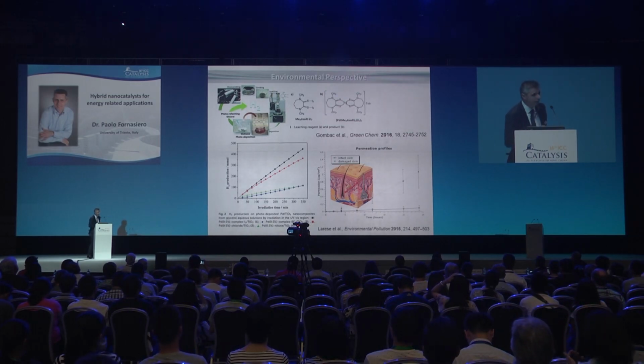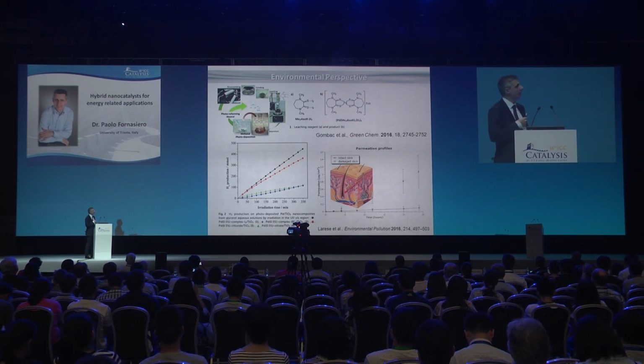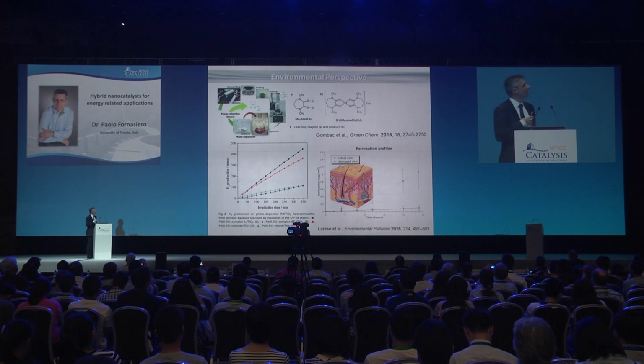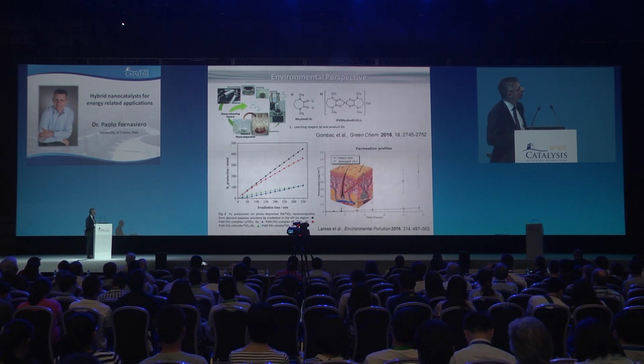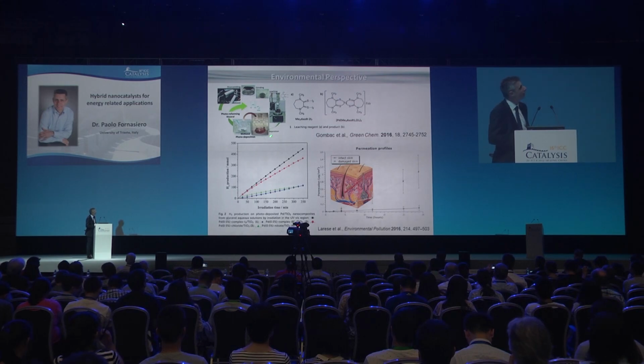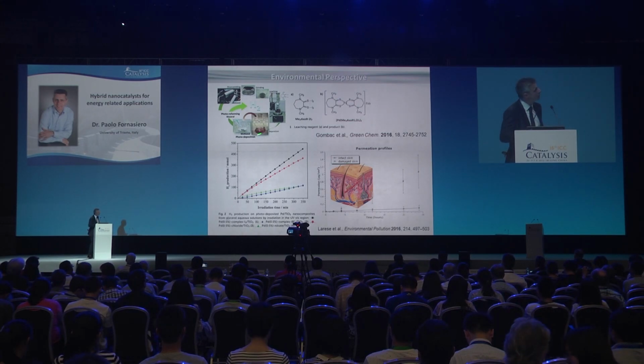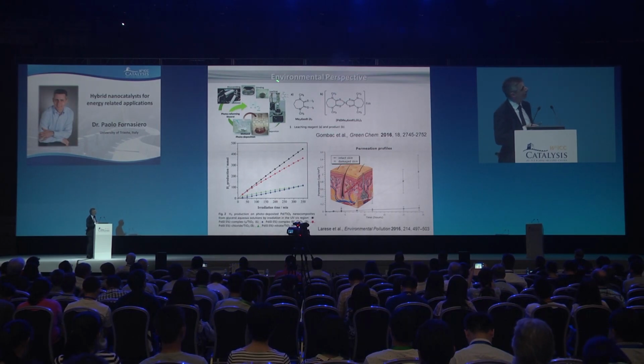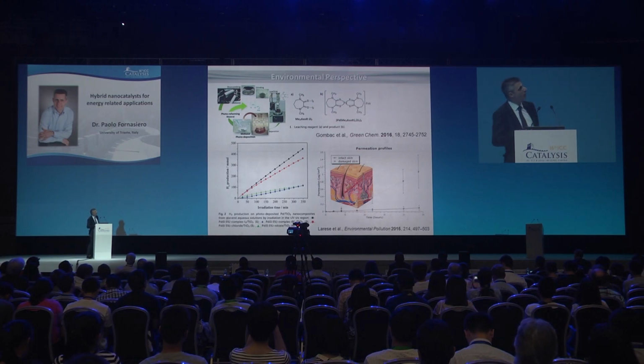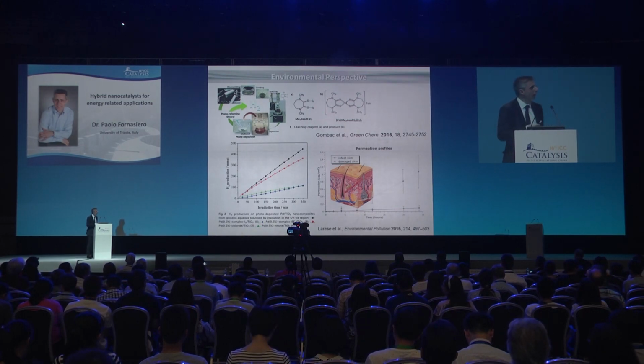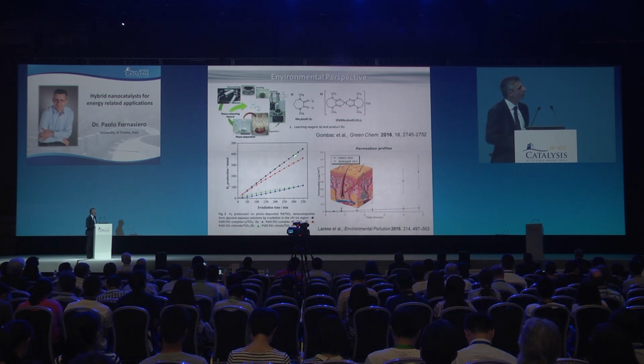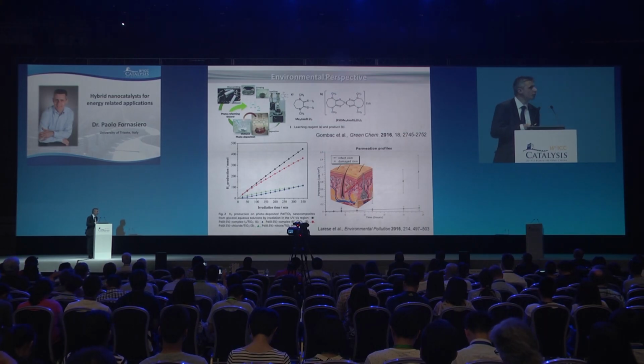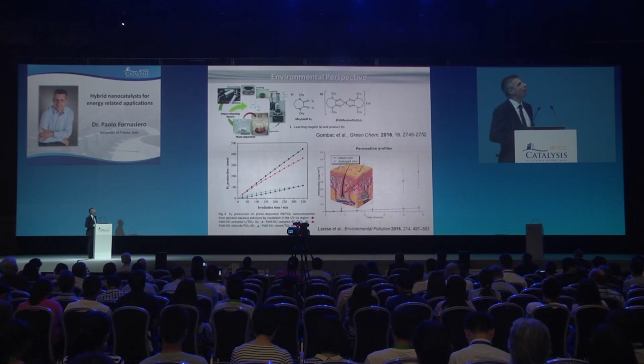Last aspect I want to point out is that in our research we always look at environmental aspects, and so we have done lots of work also in the area of recovering material from spent catalysts, like recovering noble metals from car converters. And we designed, we patented, and just published a process in which we can extract palladium in quite mild conditions, obtaining this type of complexes that are also very useful in the preparation of photocatalysts, which show very high hydrogen evolution, thanks to the possibility to incorporate in the catalyst part of these components as